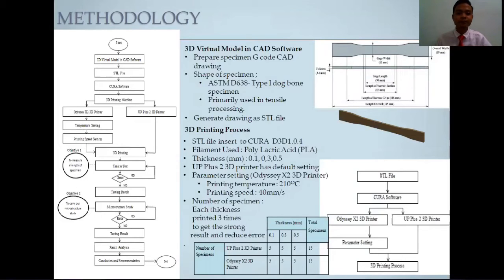The STL file that is generated, we will insert it into the 3D printing machine software, which is Cura D3D 1.0.4. As I said earlier, in the scope of my project, the filament used is PLA, and the layer thickness set during printing is 0.1, 0.3, and 0.5 millimeter. The UP Plus 2 3D printer machine has a default printing temperature and speed, which are 210 degrees Celsius printing temperature and 40 millimeter per second printing speed. So for the Odyssey X2 3D printer machine, we set the printing temperature and printing speed the same as the UP Plus 2 3D printer.